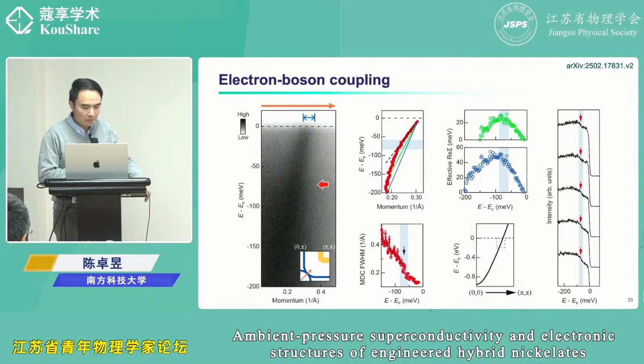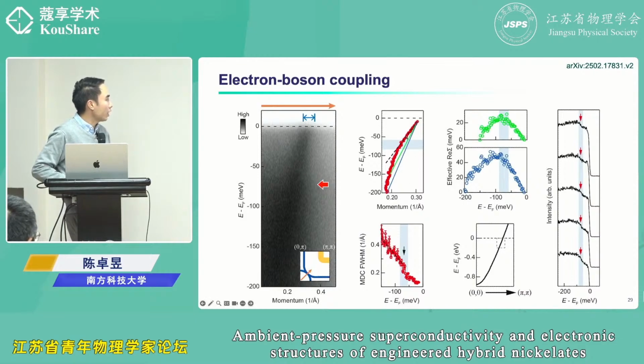Another important thing from cuprates and also iron-based superconductors is what is sometimes called kinkology. Because of bosonic mode coupling, the band structure is renormalized, and then you see a kink in the band structure from ARPES measurement. If it's DFT, it should be pretty straight in this regime. But in the actual ARPES measurement, there is definitely a kink, and it should be a result of bosonic mode coupling.